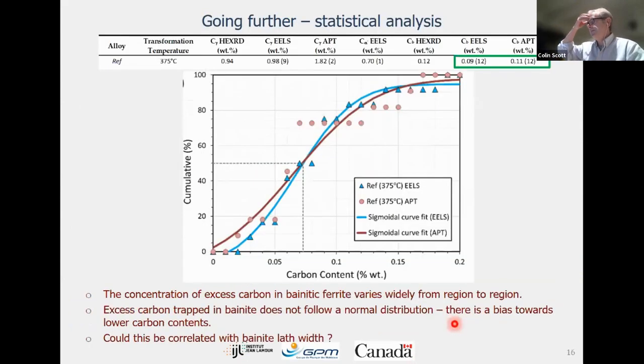So this is my last slide. We can actually go a bit further with this study because we have statistical data. So if we look at the sample, we have the best data. This is the reference sample, no vanadium, transformed at 375 degrees C. We have 12 atom probe tips, and we measured 12 different bainitic laths with the yields. And these are the average carbon contents that we found from the two techniques.